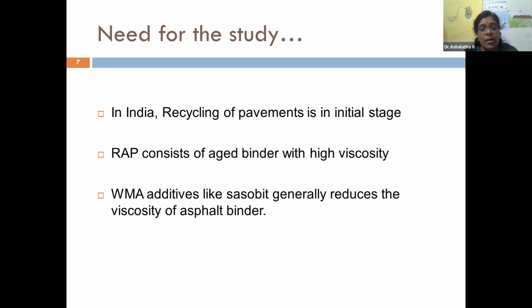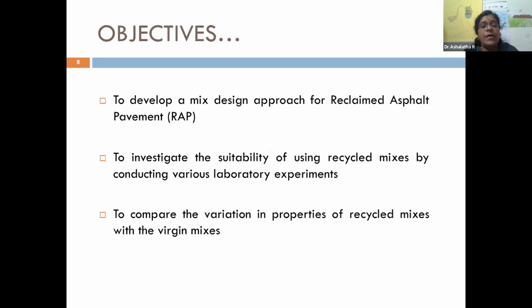Of course, now we have improved a lot, and the RAP, which consists of this aged binder with high viscosity, when we add the WMA additives like Sasobit, it generally reduces the viscosity of the asphalt binder.